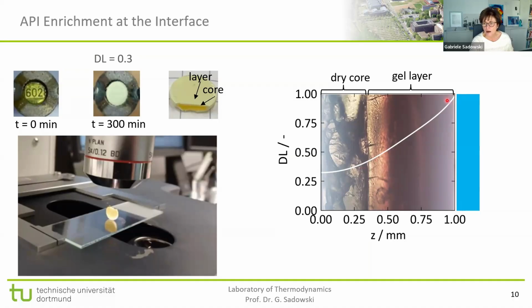the modeling said at the outer area of our tablet, that means here in this yellow light area, we have an almost polymer-free layer where we have the hydrophobic API. And this very nicely also agrees with the experiment. So we analyzed the outer part of the gel layer, and of course we also analyzed after the experiment what the concentration in the dry core, which was still dry, was, and this was very nicely coincident with our modeling.